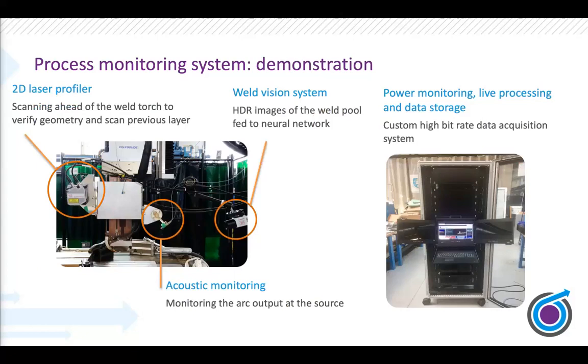Within the system, we were demonstrating three sensors into the data acquisition system. So that's three on the head in conjunction with the power monitoring. As I said, we've got a 2D laser profile set up, scanning ahead of the weld to inspect the weld geometry. And then as we're doing multi-layer welding, we're inspecting each of the subsequent layers as they're deposited. We've got acoustic monitoring, listening to the arc and looking for disturbances in the acoustic profile given off by the welding. A weld vision system retrofitted to the weld head, implemented by TWI.